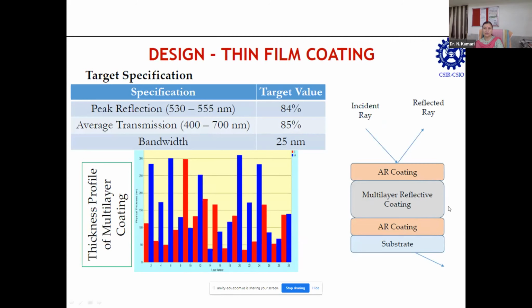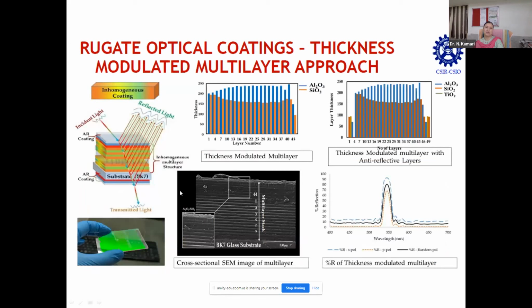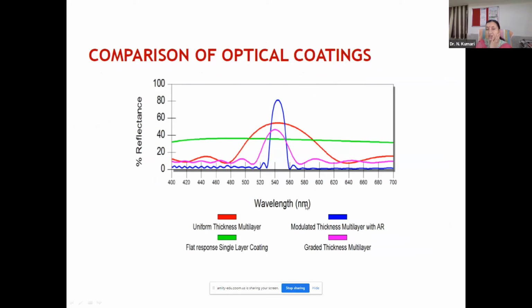And also the final result, if I show you, this is what we have received. These are the number of layers, almost 44 layers it involves, and this is the substrate, the BK7 substrate, and also we are able to achieve very low reflection outside the window, and highest reflection inside. And this is the actual sample which is shown here. You can see that when the white light is on, green light is reflected. So this kind of application requires basically a single wavelength reflection.